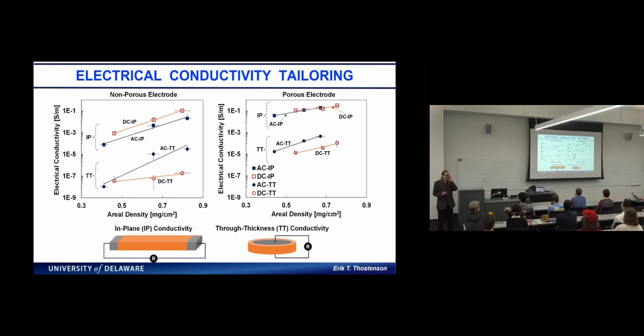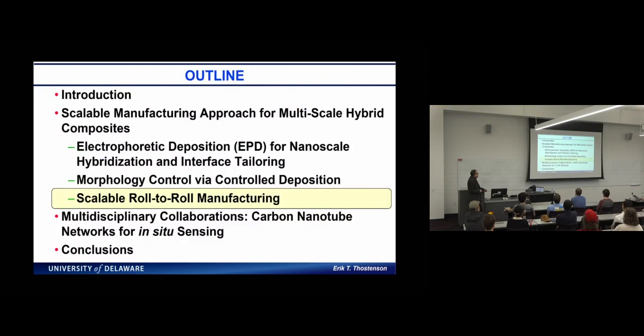So these are just under different conditions of deposition, looking at how we're changing the electrical properties, both in plane and through thickness of a fiber composite. And this electrical conductivity tailoring, it's not that we're necessarily looking to control the electrical conductivity, but that is what gives us that ability to do piezoresistive sensing. And this is also something that we've looked at as quite scalable. As I mentioned, it's something we can do in the lab, and we make a couple of square inches of material.